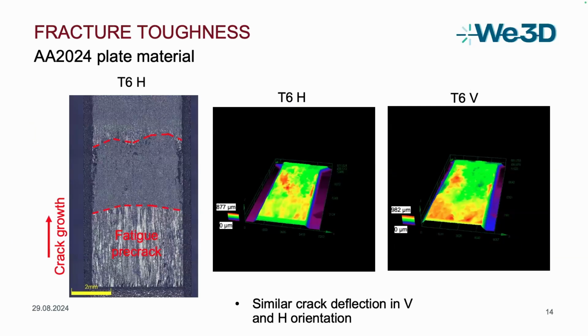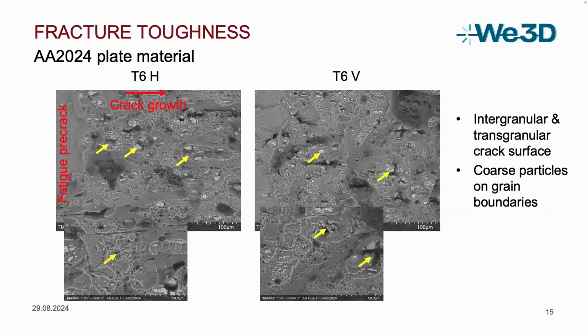Here we have an evaluation of the crack deflection for the plate material in the condition T6, horizontal and vertical. We can see that we have rather a flat crack, a straight crack propagation with below 1 millimeter for the whole sample here. And in the SEM, we can see that we have basically intergranular and transgranular regions with dimples in the transgranular regions because we have a quite high fracture strain in this material, but also with some coarse particles on the grain boundaries.